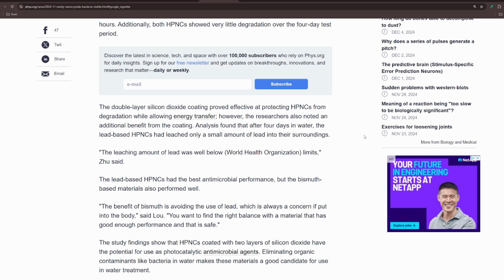However, the researchers also noted an additional benefit from the coating. Analysis found that after 4 days in water, the lead-based HPNCs had leached only a small amount of lead into the surroundings. The leaching amount of lead was well below WHO limits.